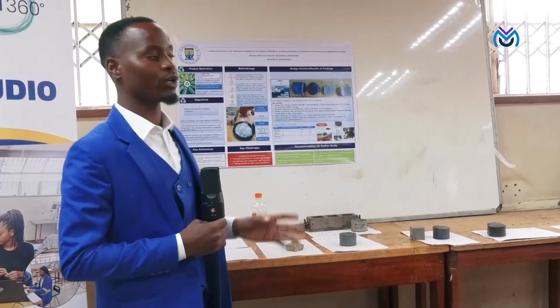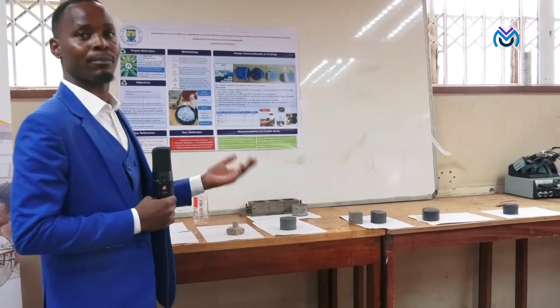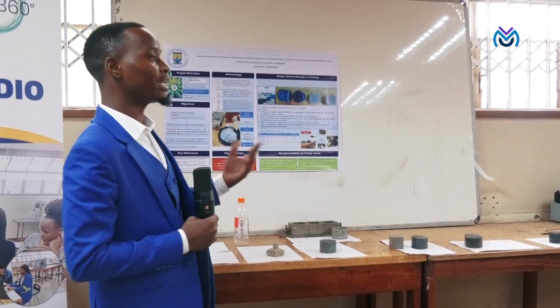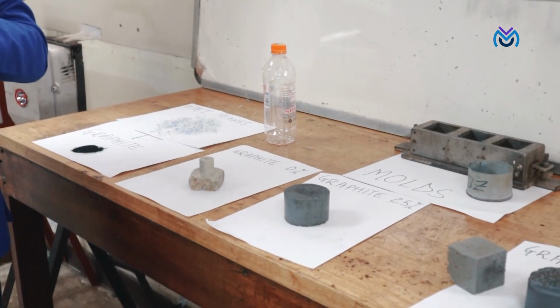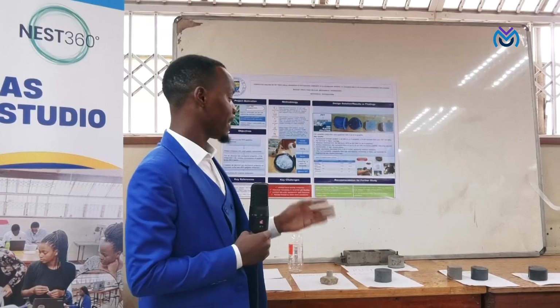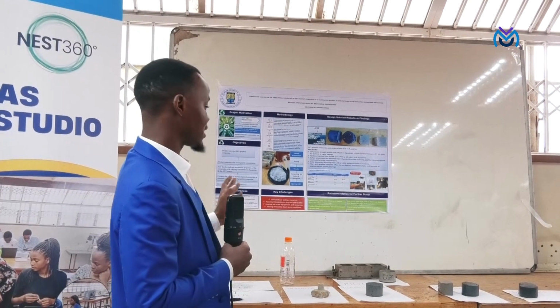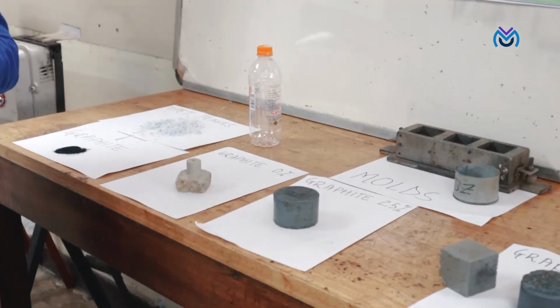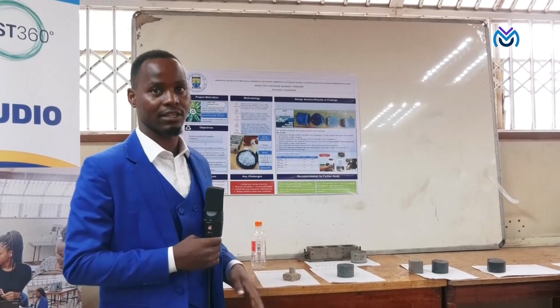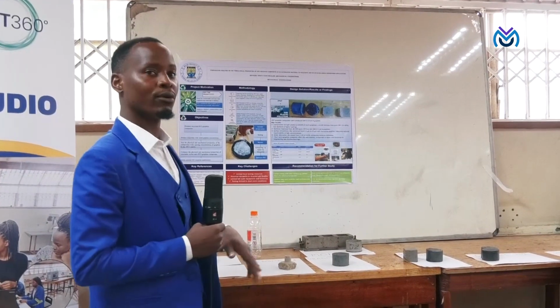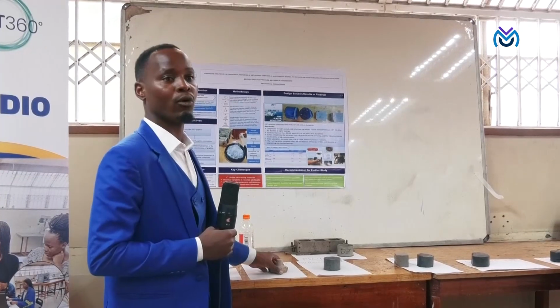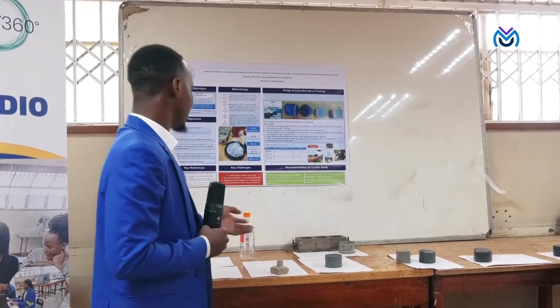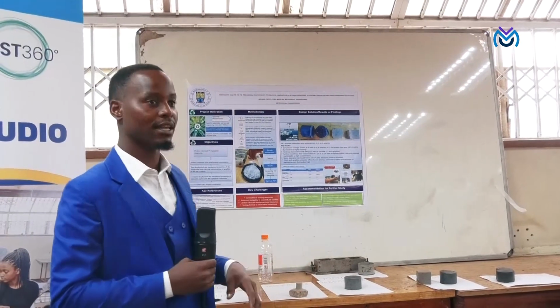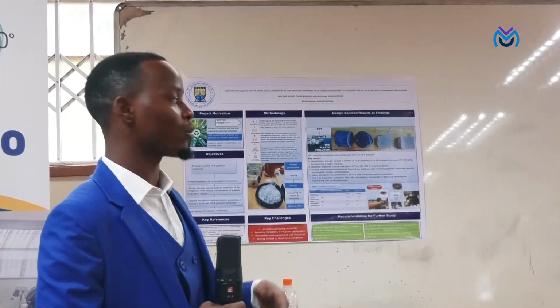90 megapascals. From there, we did the water absorption tests, in which we took our samples and put them in a water bath maintained at a temperature of 25 degrees, and we waited for 24 hours. After 24 hours, we took the mass of these samples and plotted a graph, and the graph showed that as we increase the amount of graphite in these samples, the water absorption decreases. So according to the graph, the sample which is optimal in terms of water absorption is the sample with zero graphite.